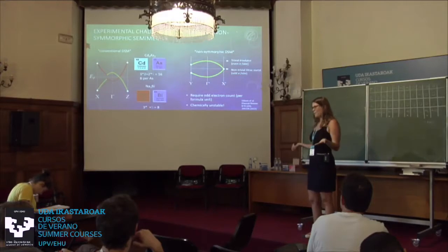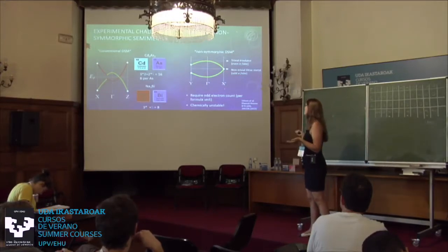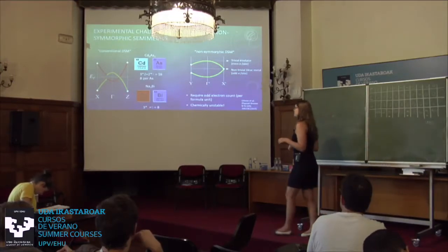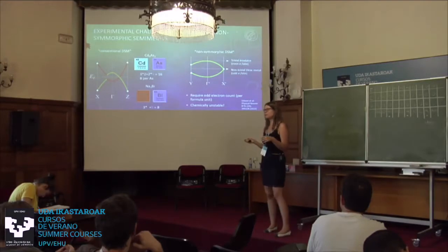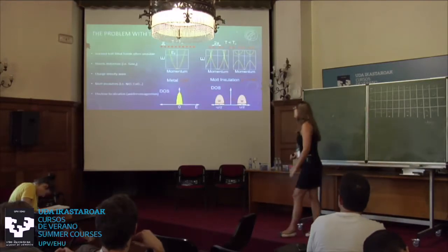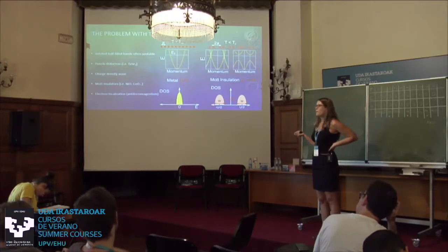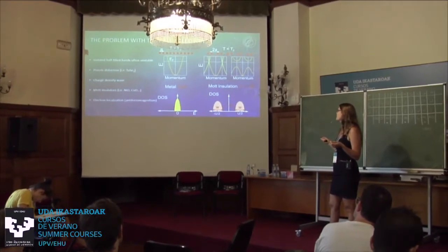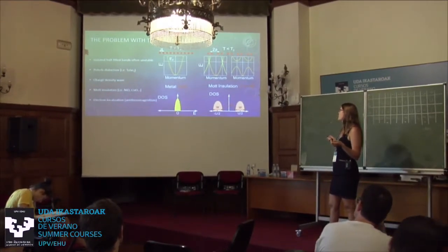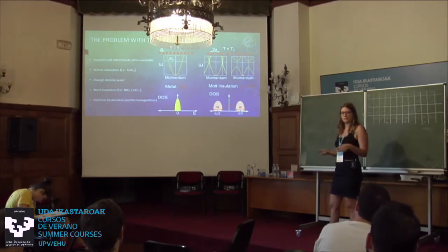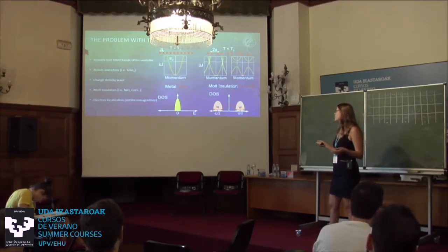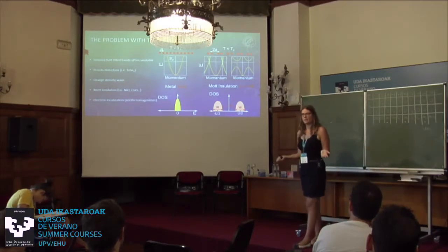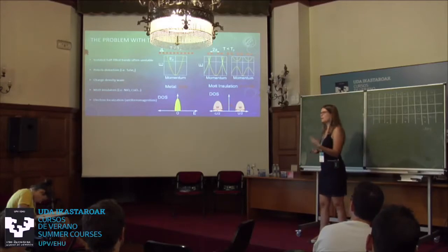And actually, even worse, if you want it to be isolated, so if you don't want any other pockets to cross, then there are lots of different mechanisms compounds like to use to avoid this kind of isolated half-band. You might be familiar with some of them. Compounds with an isolated half-filled band like to undergo Peierls distortions or charge density waves, so they distort the lattice to actually reduce this crossing and gap it out. Or they like to be Mott insulators, which does the same trick, so the crossing we care about gets gapped and it's not there anymore. Okay, so we need to find a trick to get around that.